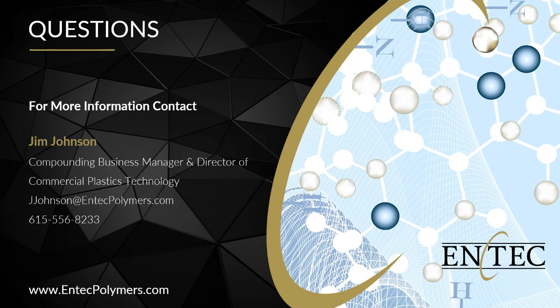There's another question here. What do you think is the best compatibilizer for blends of polypropylene and Ziegler-Natta linear low density polyethylene to provide high clarity, tough packaging film? In this case, I would recommend a maleic anhydride modified polyolefin, and specifically for that application, the Dow Retain material would be the product that I would recommend because it was developed specifically for film recycling to compatibilize dissimilar polymers, in particular nylon and EVOH, into the linear low density. So it not only compatibilizes, but it's also designed to improve properties as well as maintain the clarity. And I think that's a key point in the question here. I would again recommend the Dow Retain 3000 material for that application.